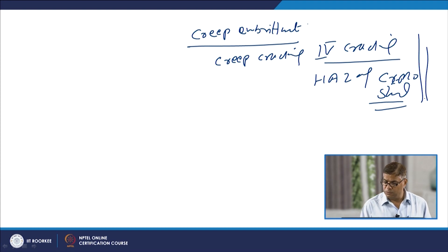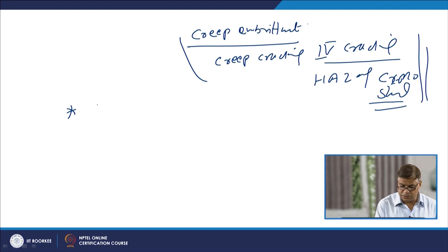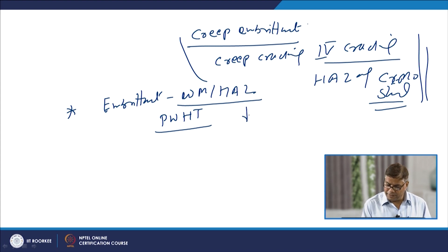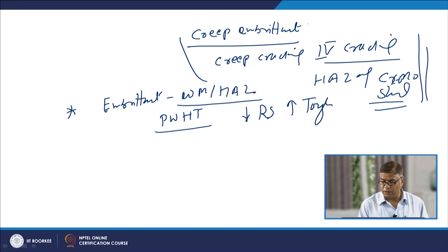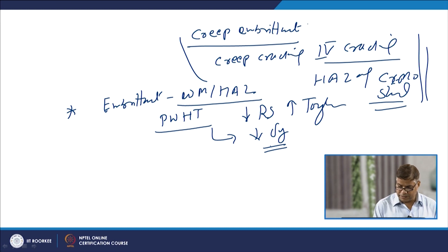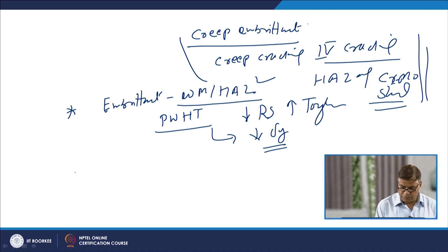We will discuss the factors that lead to creep embrittlement. To avoid embrittlement of chromium-molybdenum steel welds in the weld metal and heat-affected zone, the best approach is post-weld heat treatment. This not only relieves residual stresses but also increases the toughness of the weld joints, though it generally reduces the yield strength of the weldment. Using suitable preheat is another measure to control embrittlement due to high-hardness martensite formation.